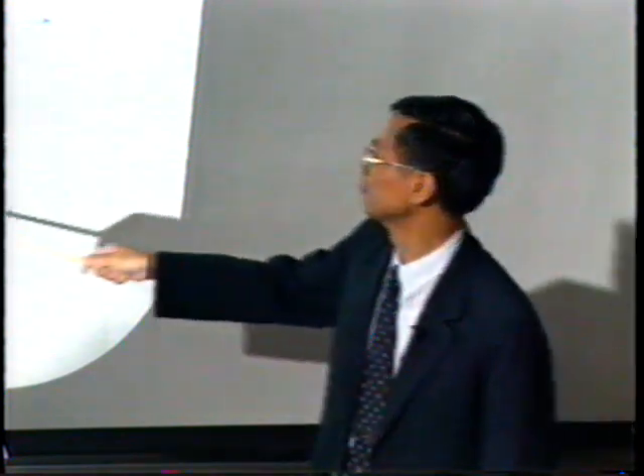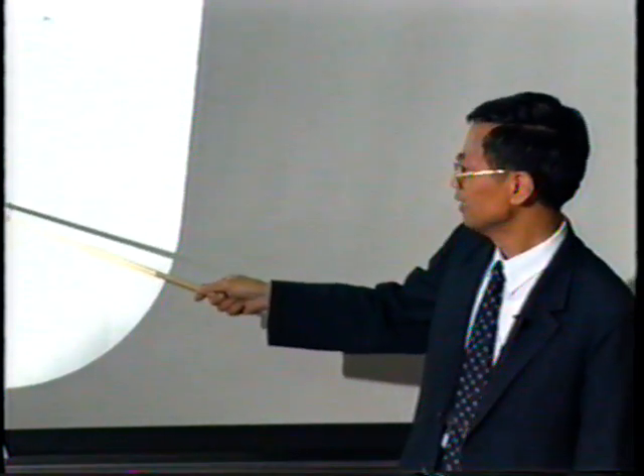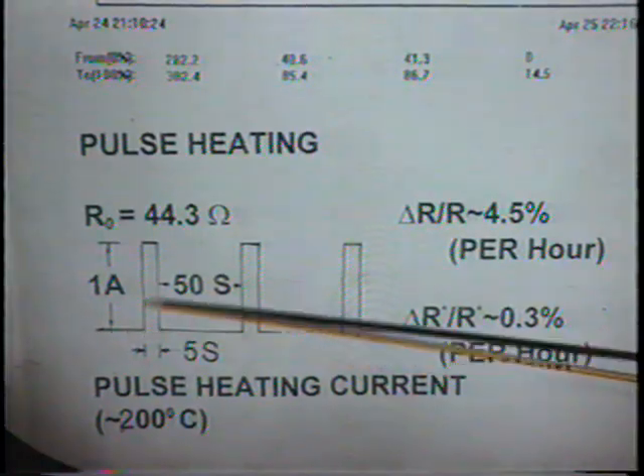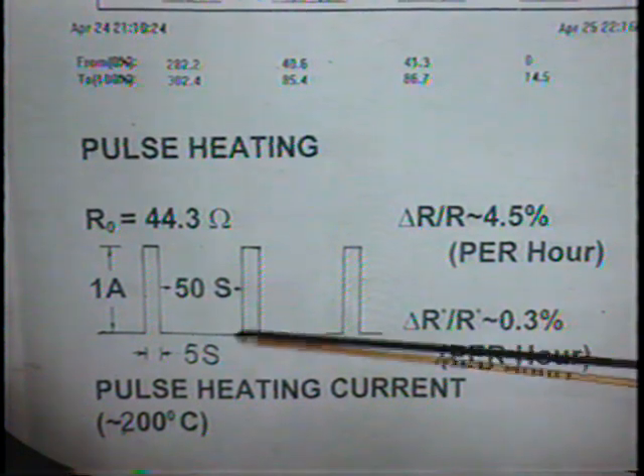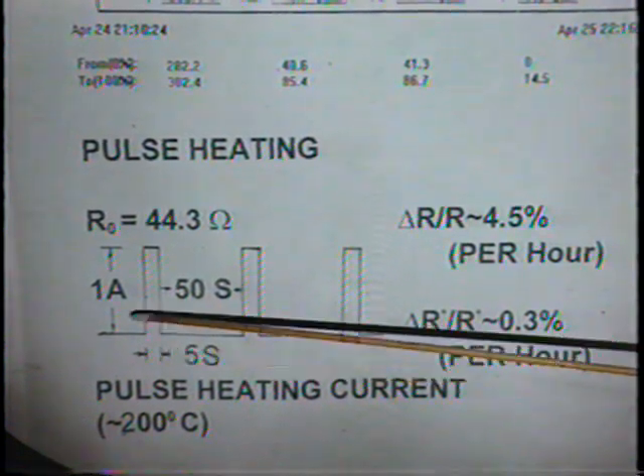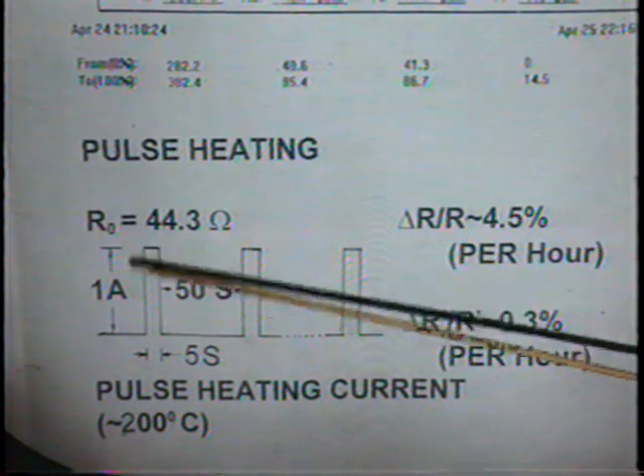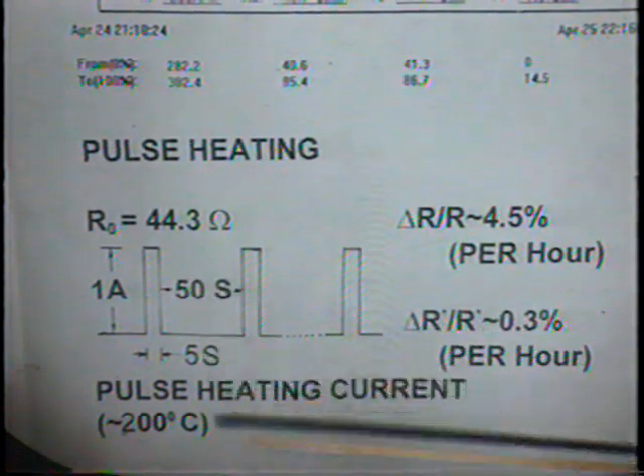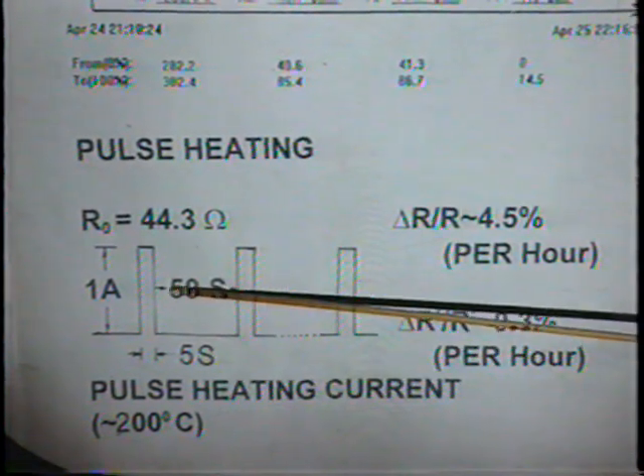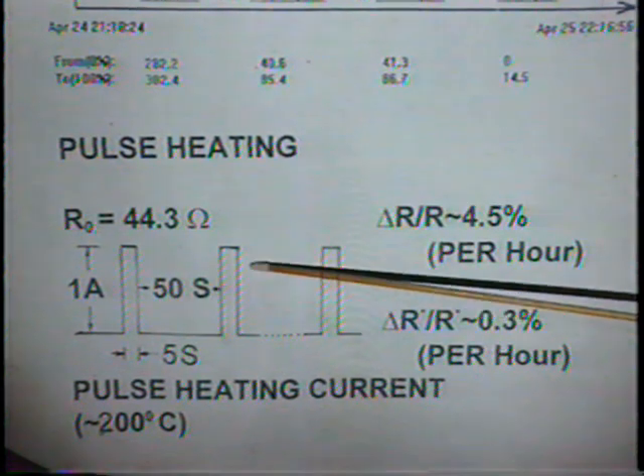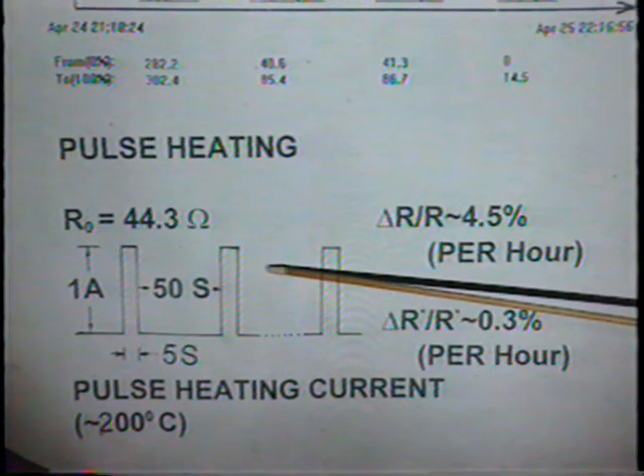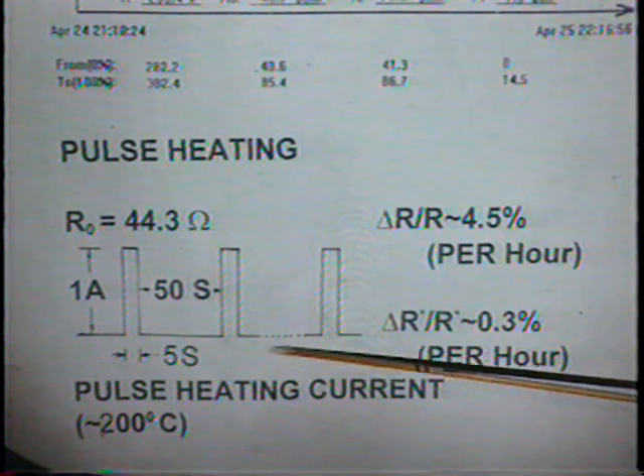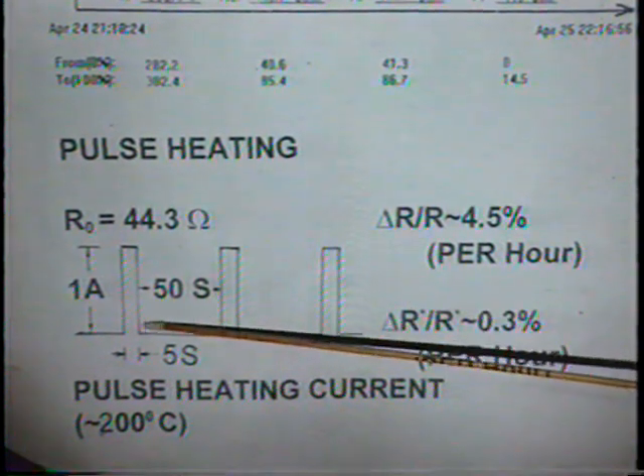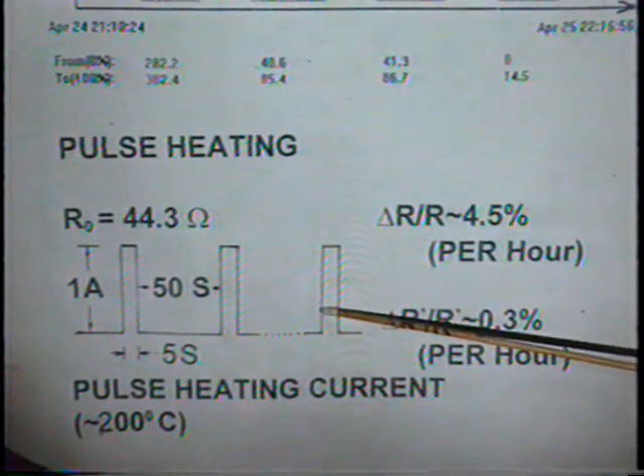The pulse heating. This is the current through the palladium wire. 5 seconds for 1 ampere. Very thin wire. Then stop. 50 seconds. About 20 minutes for this. Then we will see a big effect on this loading.